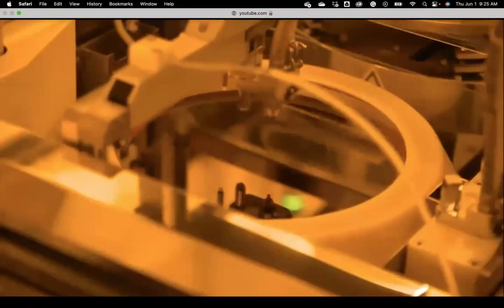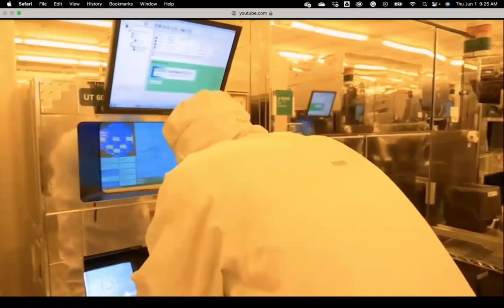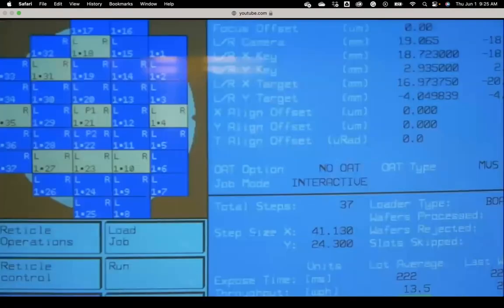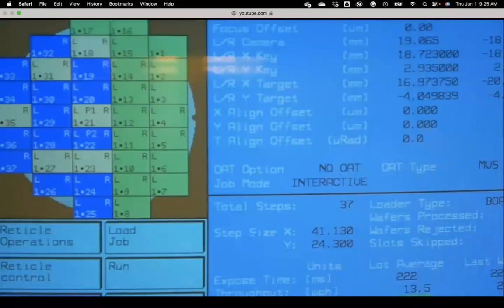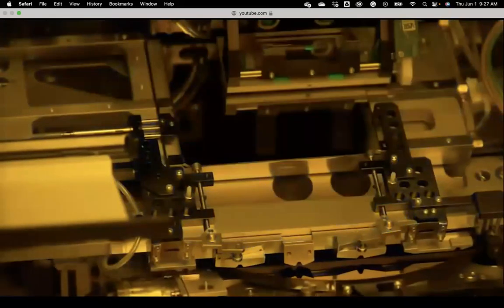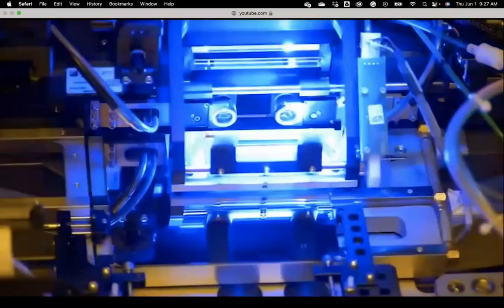The wafer is then exposed to light through the photomask in special exposure machines known as steppers. During this process, coaster-size areas of the chip template, known as reticles, are used to transfer the complex geometric patterns of the circuit design to the silicon wafer. The exposed area of the chip pattern is developed, revealing the layer of oxide below. The unexposed part remains as is, protecting the layer of oxide.